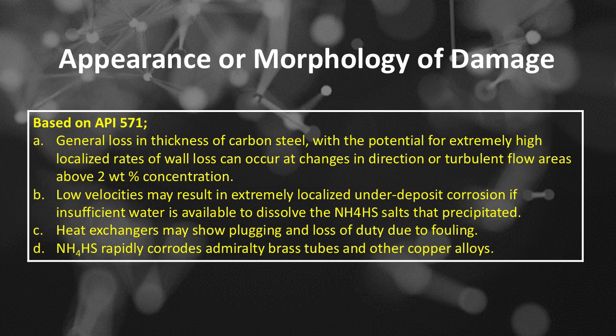Ammonium bisulfide corrosion or alkaline sour water. Appearance or morphology of damage based on API 571. Number A: general loss in thickness of carbon steel, with the potential for extremely high localized rates of wall loss at changes in direction or turbulent flow areas above 2 wt% concentration. Number B,